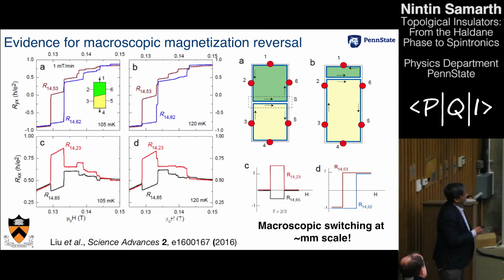Just to give you some idea of the length scale, the typical spacing between these contacts over here is about 500 micrometers, or half a millimeter. Okay? What we do now is, as you are measuring the sample, you measure, for example, the Hall voltage over here, this pair of contacts, and this pair of contacts simultaneously as you sweep your magnetic field. And what you find is that this Hall voltage jumps, or this resistance jumps first, and this resistance jumps at a later stage, at a higher magnetic field.